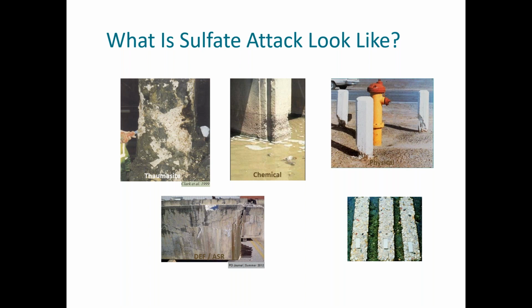And then I made sure to put in the title of this picture on the lower left, DEF, which is delayed ettringite formation / ASR, because I know that there are probably some people that will say, well, DEF and ASR happen together. You never see them not happen together. And ASR is alkali silica reaction, and you do very commonly see them together. But there is a lot of debate as to whether you have to have ASR to experience DEF.